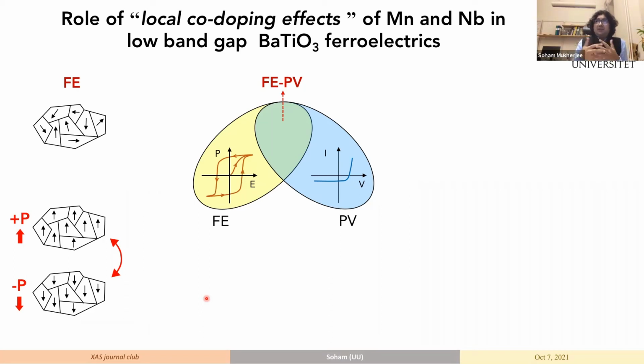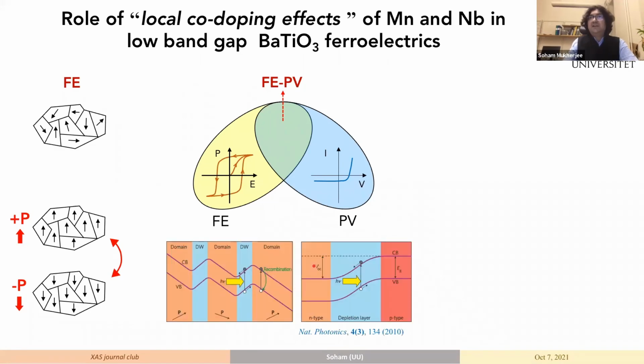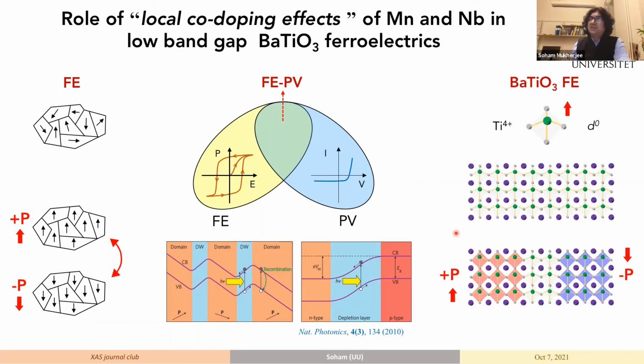So ferroelectric photovoltaics are extremely important, and more and more work has been done in recent times. I'll not go into the details, but the catch is that there are domains in the material, and because of these domain walls, you can have very high open circuit voltage. And this is why ferroelectrics are being much more explored for their photovoltaic performance. So we have taken a barium titanate material.